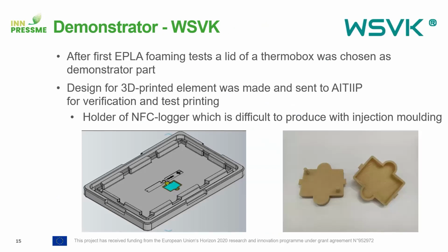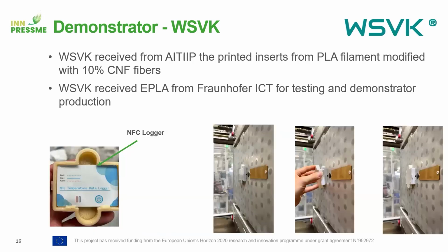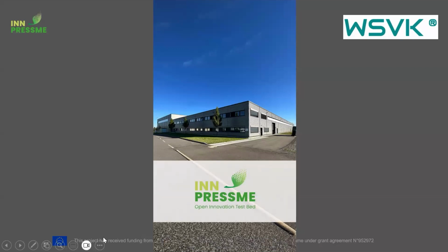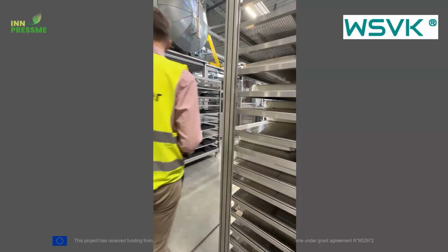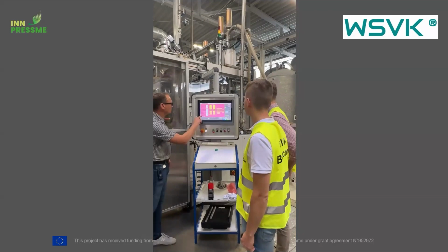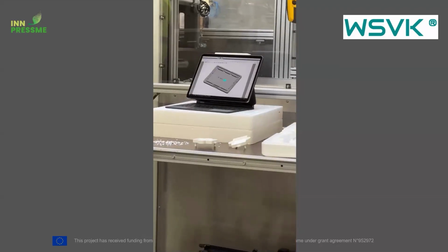Then at partner WSVK, the whole demonstrator process was implemented, meaning that they chose a special tool, which was in this case a lid of a thermal box. And they also designed this holder, which was printed by AITIIP. And both were then, together with the PLA bead foams from Fraunhofer, sent to WSVK for the demonstrator production. And WSVK made a short video to give you an impression about how this demonstrator production took place at their production plant.